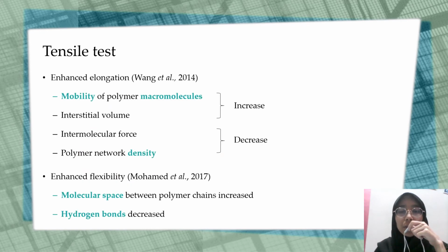Citric acid helped to increase the macromolecules mobility and interstitial volume of the polymer, which decreased the intermolecular force and density of polymer network, enhancing their elongation. The modified bioplastics also have increased molecular space between their chains and decreased hydrogen bonds, improving their flexibility.